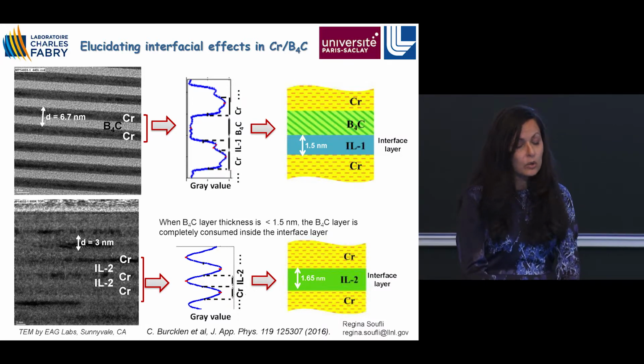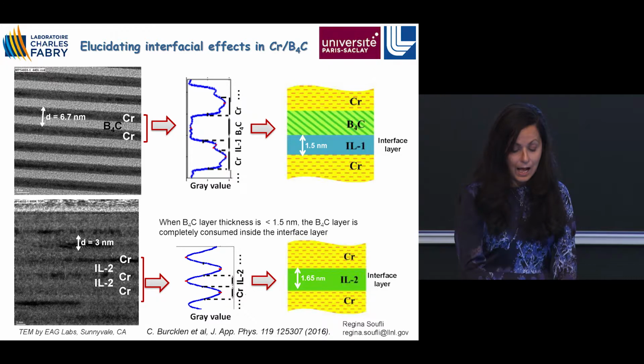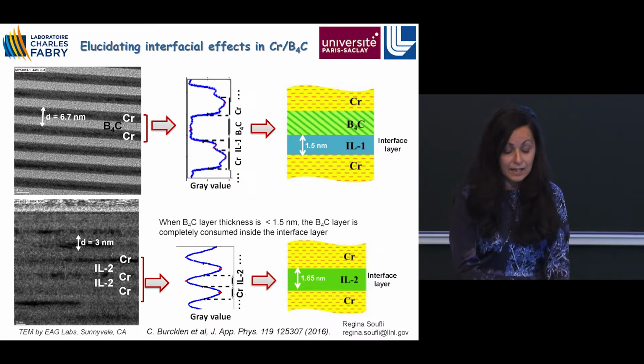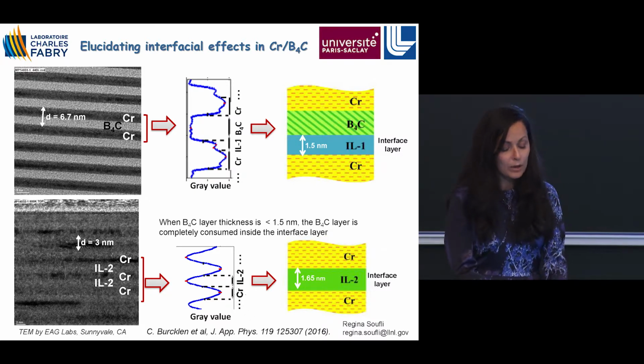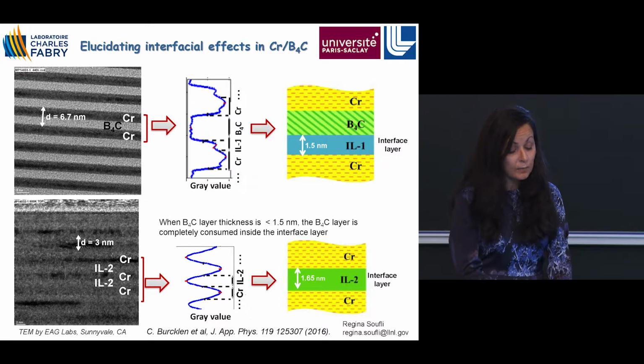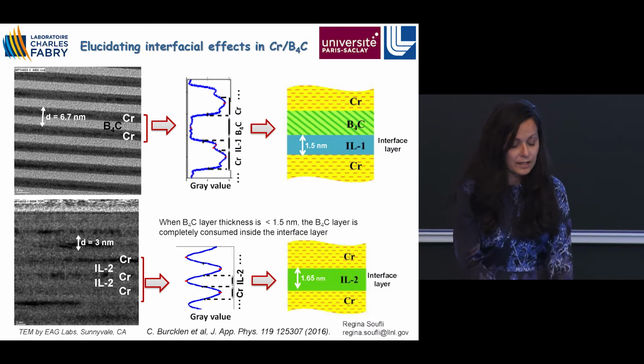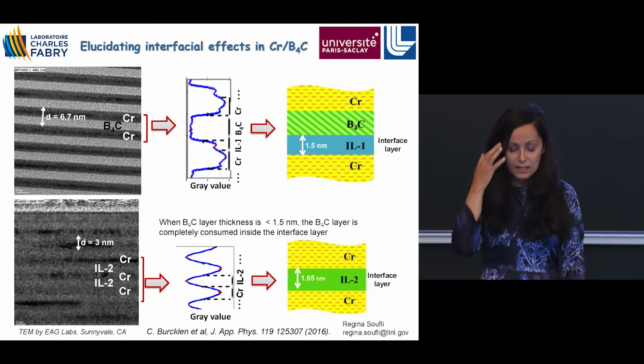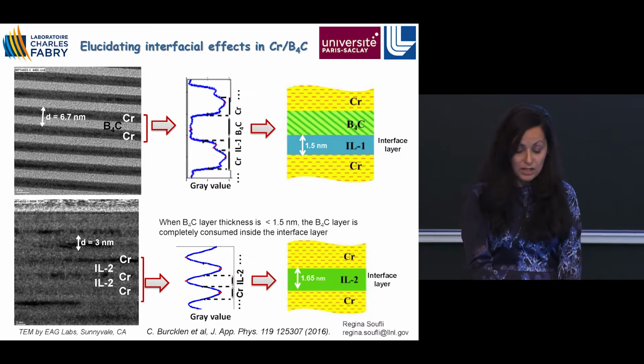So we're taking a closer look in the multilayer structure by doing cross-sectional transmission electron microscopy, or TEM, that I was mentioning earlier. Here we have two different samples, sample 1 and sample 2. Both of these samples have the same targeted thickness of chromium layer. It is 2.5 nanometers. The top sample has a targeted boron carbide thickness of 5.7 nanometers, while the bottom sample has a much thinner boron carbide layer of 1 nanometer. First observation clearly is that the top sample has a well-defined periodic structure, while the bottom sample seems disordered, non-uniform, with loss of contrast between the layers.